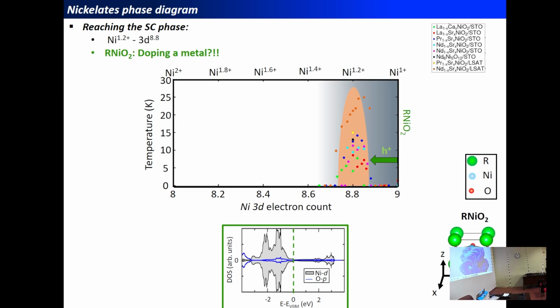And therefore, to reach the superconducting region, we have to dope a metal, which appears to be rather counterintuitive because usually, to reach the superconducting region in oxides, such as in cuprates or bismuthates, we start from an insulating material and we try to dope it to reach the metallic superconducting region. Nevertheless,